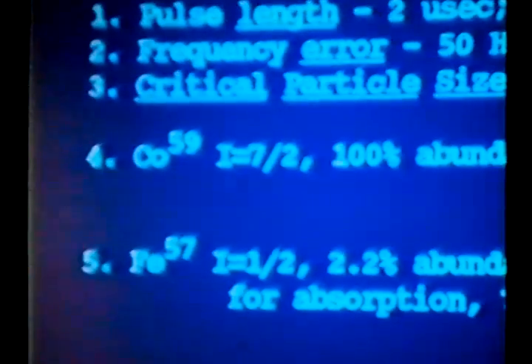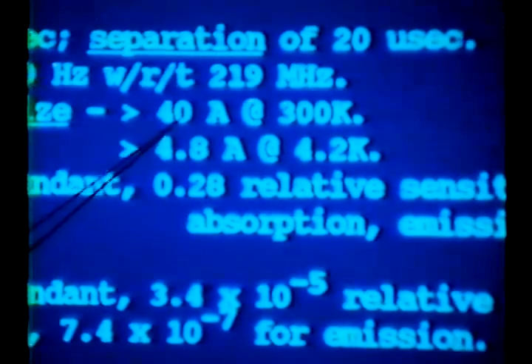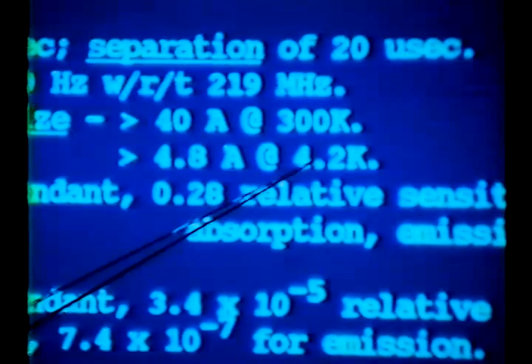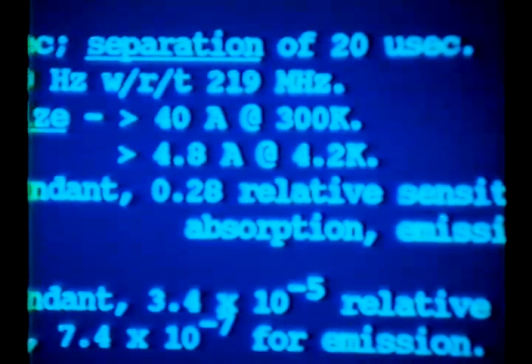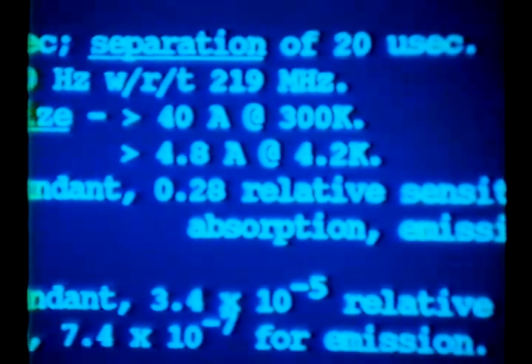It's quite useful. There's a critical particle size to this experiment: you can see particles greater than 40 angstroms in size at room temperature, and you cannot see particles that are around 5 angstroms at liquid helium temperature. So in liquid helium, we don't see a signal, and we know they're metallic and small, around 5 angstroms or smaller.